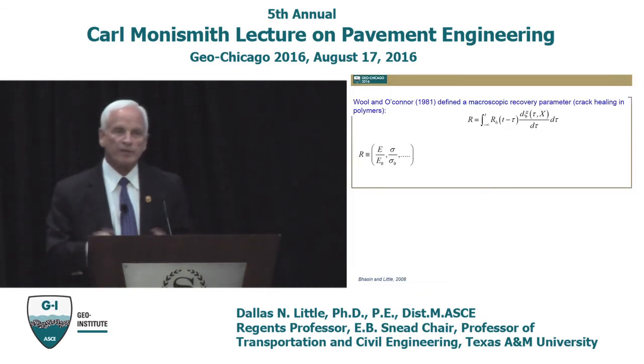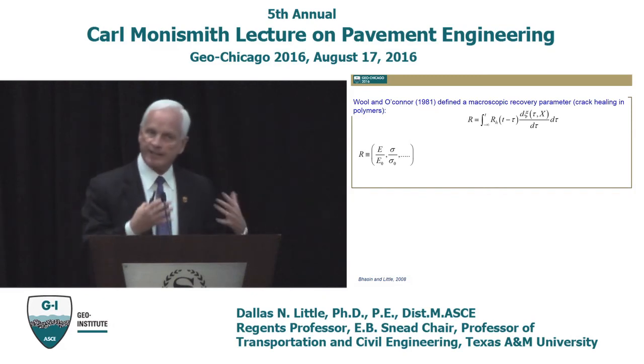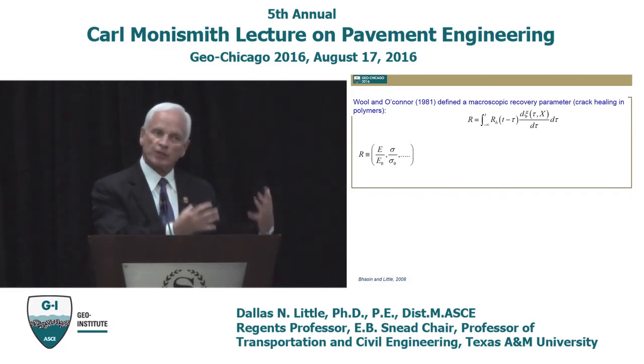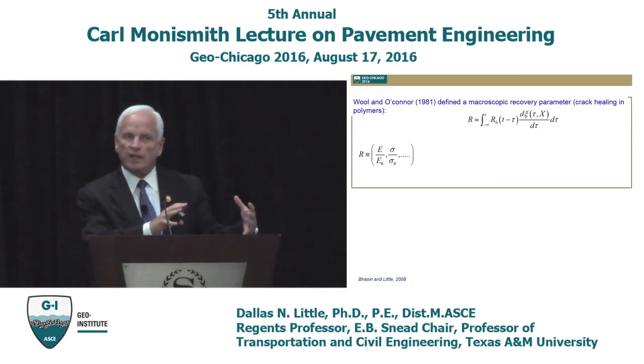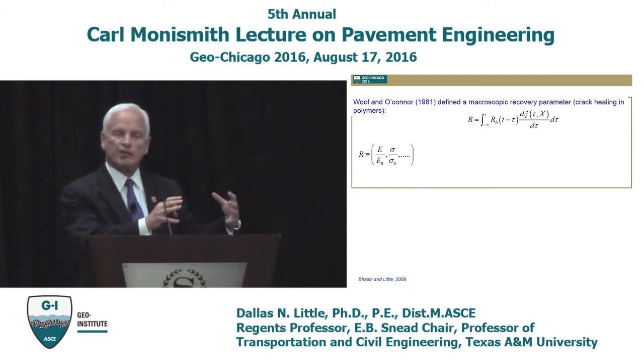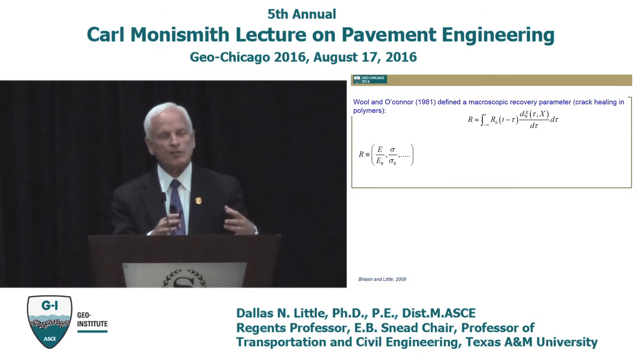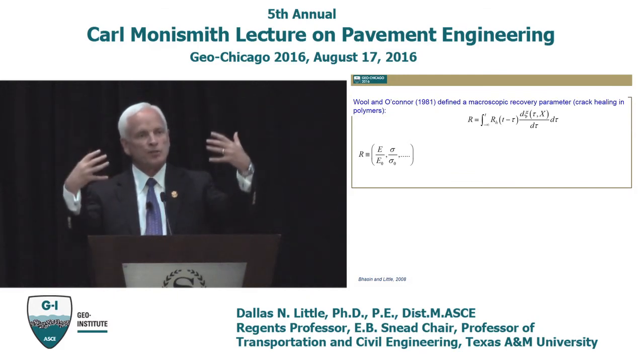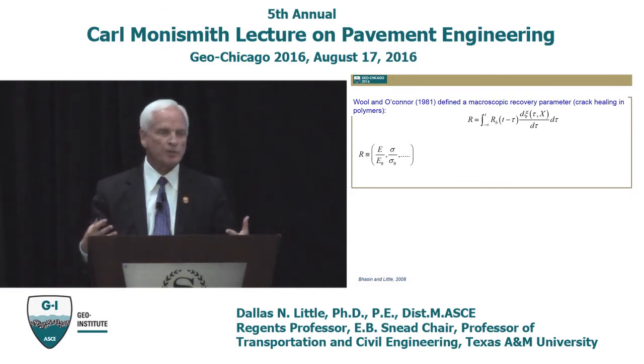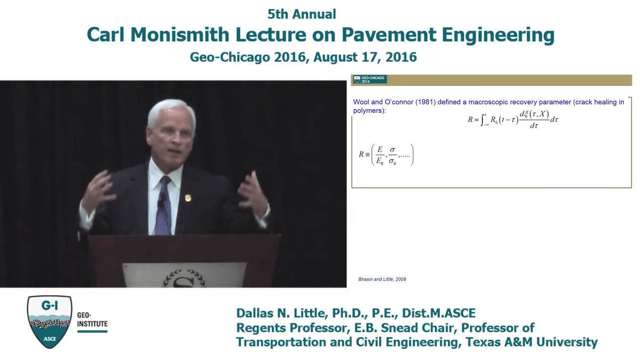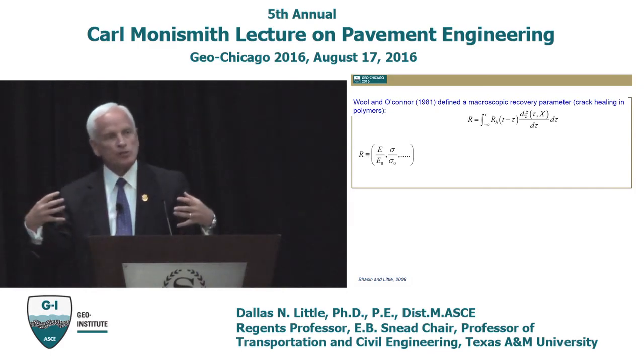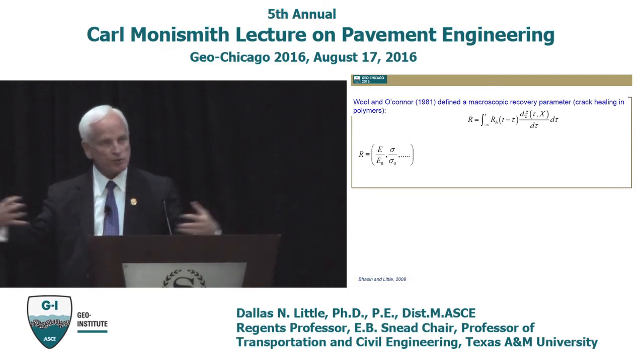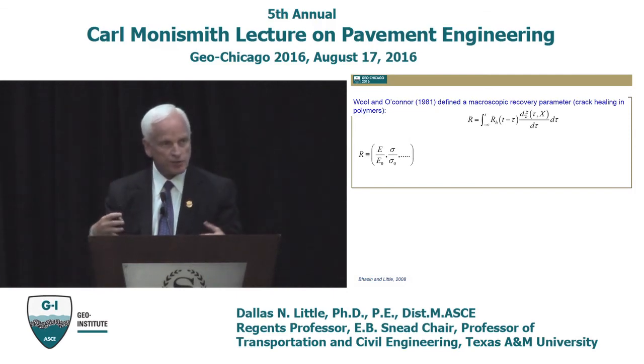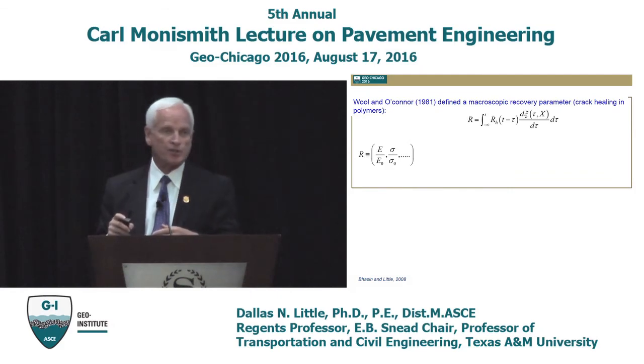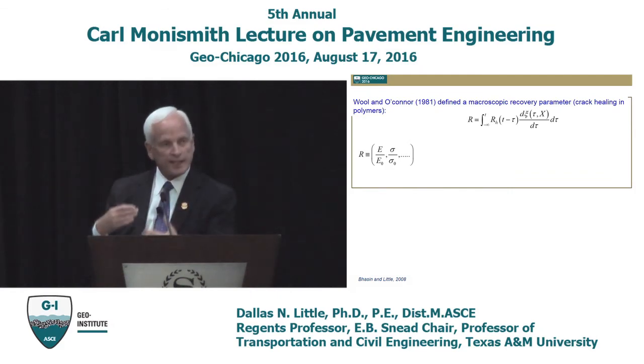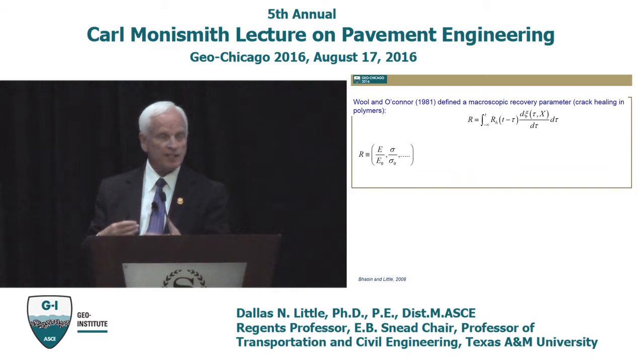Now, so we've got a way to calculate damage. And this damage we're looking at is really, we're viewing it as a series of microcracks that are compromising the integrity of the area that is resisting load using continuum damage mechanics. The Y function, which is driven by shear stresses and which is mediated by confining pressures, drives this damage force. There's something that's working against this damage force, and that is healing.